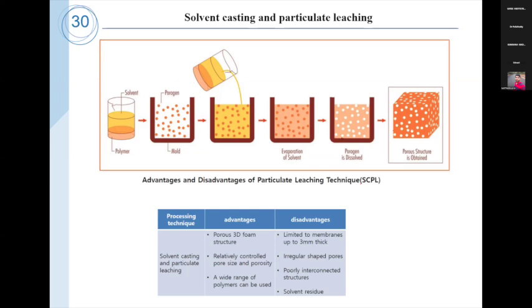So the pore size and porosity depend on the size of the porogen particles like sodium chloride. If the porogen particle size is higher, then we can produce high porosity and high pore size. So it is a simple technique. This technique has some advantages and disadvantages. The advantages are that it can produce a porous 3D structure with relatively controlled porosity and pore size.